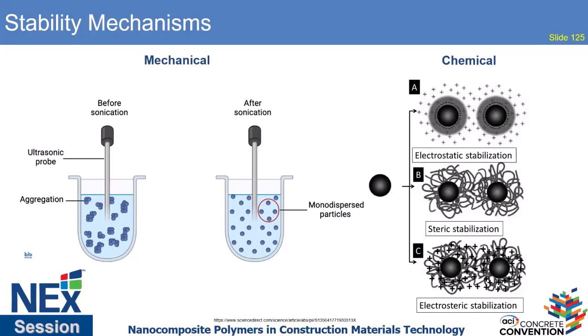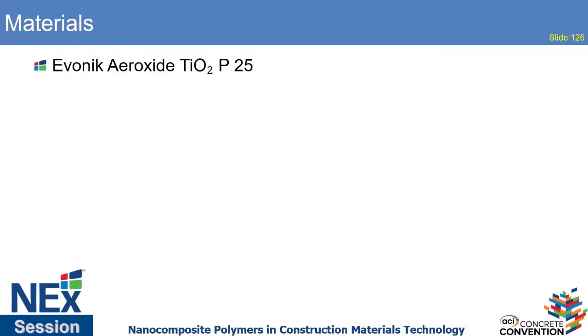The electrostatic stabilization, which will be the focus in our presentation, is typically when you're using anionic surfactants and something known as a double layer forms around the particle. As the particle moves, a small part of the liquid moves with the particle. The place where the shear plane is, basically the edge layer, is where we are calculating the zeta potential, which is the measure of the electrostatic repulsive forces.